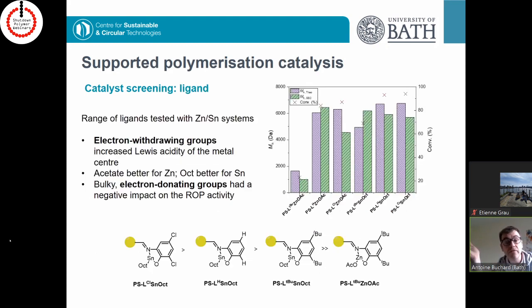So the second thing for us was to have a look at whether the ligand structure had any effect at all on this activity, and the conditions of the reaction here are exactly the same, looking at melt polymerization at 130 for 24 hours, even if it's an overkill, and I'll show that in a minute. What we could see clearly is there was an effect of the ligand structures, even when supported. You could see that electron withdrawing groups that are thought to increase the Lewis acidity of the metal center were